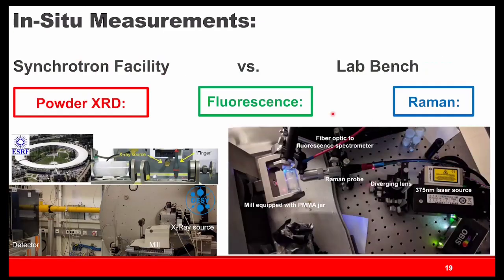From a practical perspective, how do we do these measurements? Well, powder XRD measurements require a synchrotron, so we've done most of these at DESY in Hamburg or the ESRF in Grenoble, France. And the idea here is very simple. We take a slightly modified ball mill where the jar sits above the mill, and we put our milling jar in here, just like you saw in the video in the introduction. We load our sample, load our milling balls. We have this shake side to side.